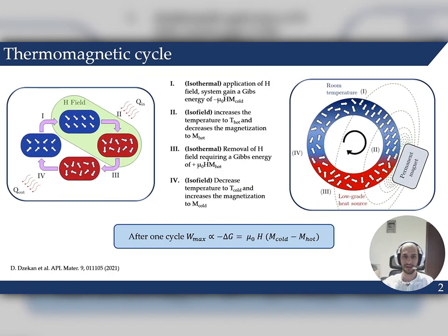But what is a thermomagnetic cycle? Well, it is a particular thermodynamical cycle composed by two isothermal and two isofield transformations. On the left of the slide is shown a scheme of the cycle. Without going into the details of the cycle, we are only interested to know that for energy harvesting application of low-grade heat, usually the hot source has a temperature below 100 Celsius degrees, while the cold one should be the room temperature. And in the end of the cycle, the system can convert heat into an amount of useful energy that is proportional to the difference in magnetization of the magnetic material used at the temperature of the two sources.